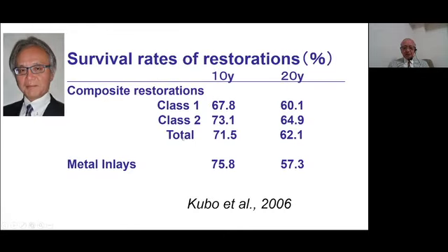My very good friend, Professor Kubo at Nagasaki University, published many papers on the survival rates of restorations, comparing direct composite restorations and cast metal inlay restorations. The results are very clear. After 10 years, the total survival rate of composite resin was 71%, and the cast metal inlay restoration was 76%. After 20 years, the composite resin restoration showed 62% survival rate, and cast metal inlay showed 57%. The conclusion of his study was that both of them were the same.